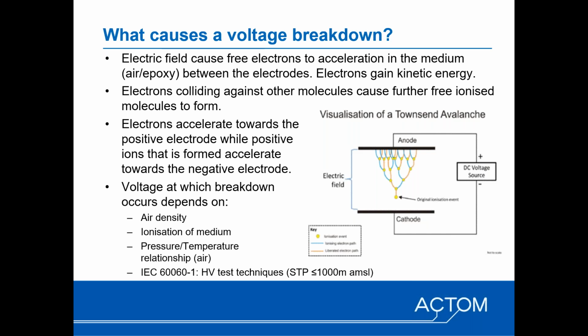Another factor that influences the voltage breakdown is pressure and temperature, and the high voltage test standard for high voltage test techniques defines standard temperature and pressure for altitudes less than 1,000 meters above mean sea level. So when you apply your insulation, or you review the insulation at altitudes above that, you need to apply certain correction factors to the applied voltage or the test voltage that you use. You either need to reduce the test voltage, or you need to actually increase the insulation that you require at higher altitudes.